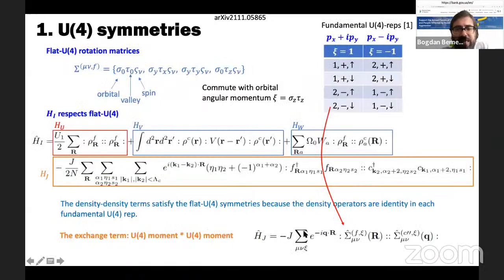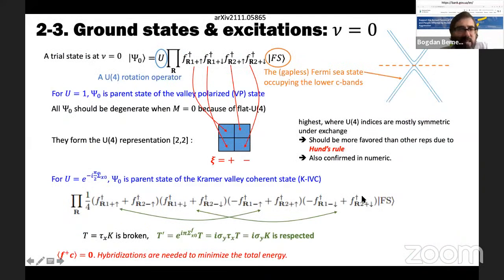And this U4 symmetry is nice. You can get the generators, but the nice thing about this U4 symmetry is you can write this term, the J term that I told you creates the topology, as a ferromagnetic coupling between the U4 spins of the f-electrons and those of the c-electrons. So now, still neglecting this, we have a much nicer form of the Hamiltonian: Hubbard U of the f-electrons, density of the f-electrons, density of the c-electrons, and local U4 moment of the f-electrons times the itinerant U4 moment of the c-electrons. And now I'll have to go very fast. If you go through this, you can understand basically the physics immediately.